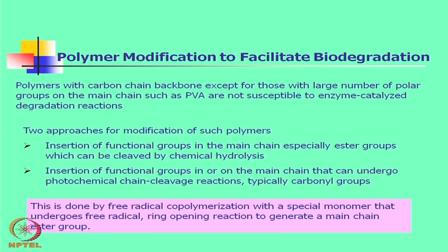But if the surface of such LDPE films can be made polar, by oxygenation, oxidized by some means, so that oxygenated groups like OH group, ketonic group, ether group or ester group are created on the surface of this LDPE by oxidation, then such LDPE can be degraded by microorganisms. So, that is a kind of modification.